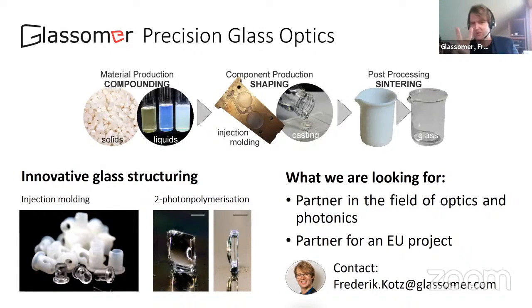Yeah, so I think it's two questions, right? The mold is basically, we can use stainless steel molds for injection molding. We also worked a lot, what you can see up here, with soft molds, PDMS molds for UV casting processes. We have a shrinkage during the sintering process, but the shrinkage is extremely isotropic because we have spherical particles within the matrix. So it's a little bit different from classical ceramic injection molding. Our standard formulation has around 60 volume percent, which correlates to 15.6% linear shrinkage. But you can go up to 85 volume percent. Then you only have around 9% linear shrinkage.